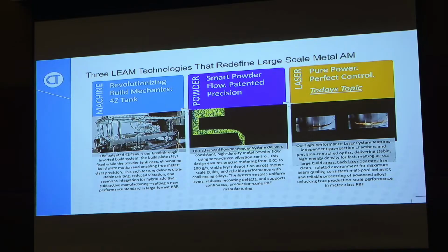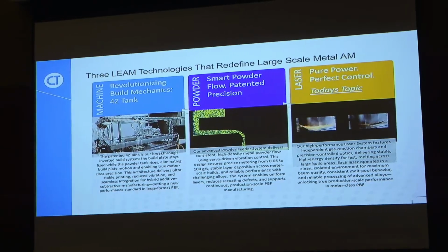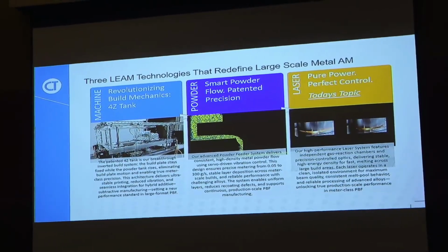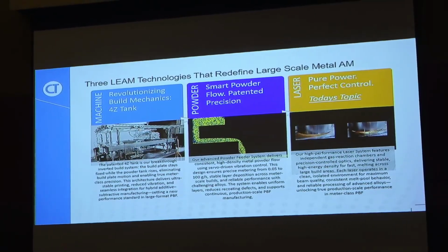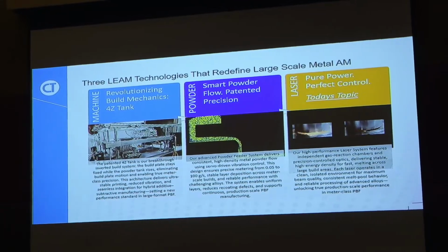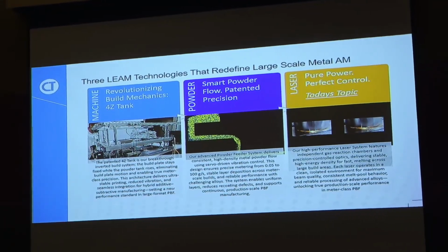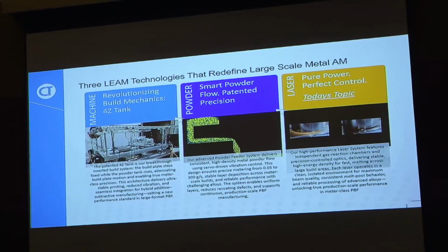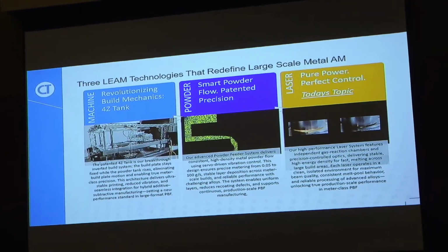The third one is the laser system in this case. That could be an E-beam, but in this case it's a laser. So when you look at the laser system, we did research and we did studies, and I'll show simulations in a sec, that typically you have galvos. And I'm not sure if everybody knows that, but galvos are basically 2 mirror systems where the laser beam is actually bent and scans over the surface area and melts the components. This is the standard AM approach, right?